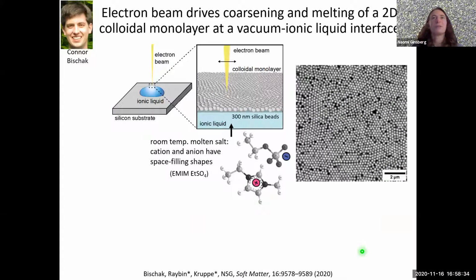Okay, so here's the setup. We make a model 2D material out of silica beads. It's initially, as you can see here, a defected solid that's pinned to an interface between an ionic liquid droplet and the vacuum in a scanning electron microscope, and it's essentially motionless. So we use the electron beam, therefore, to excite the system or to impart energy to these particles, but also to watch the ensuing phase dynamics.